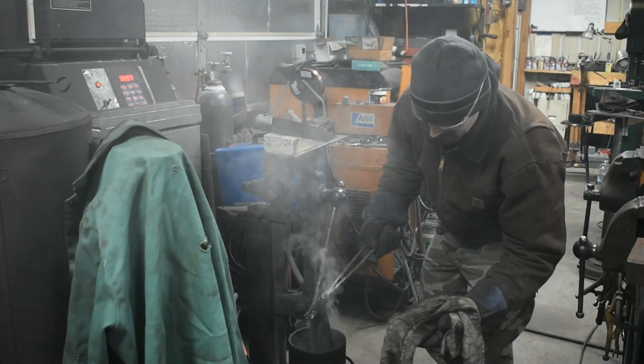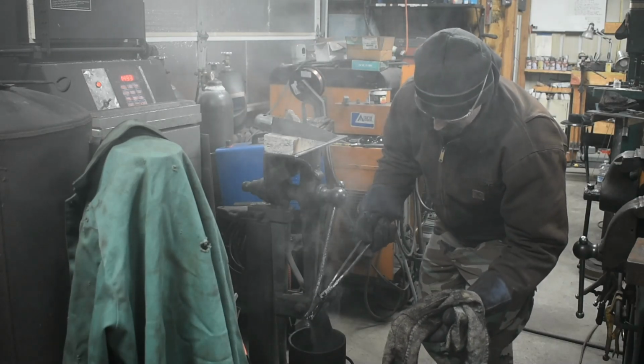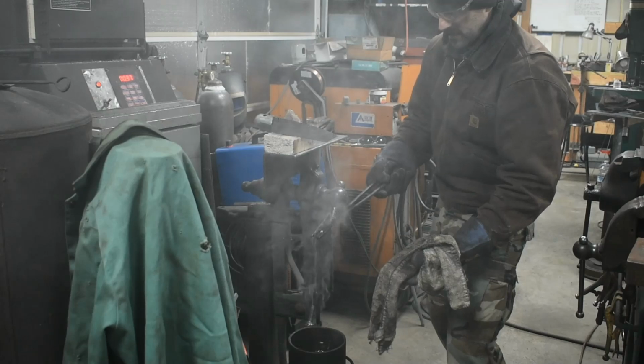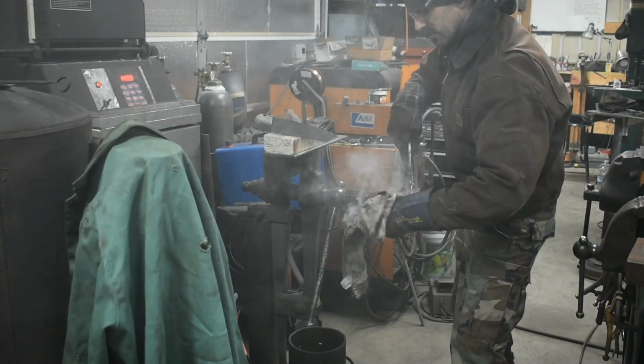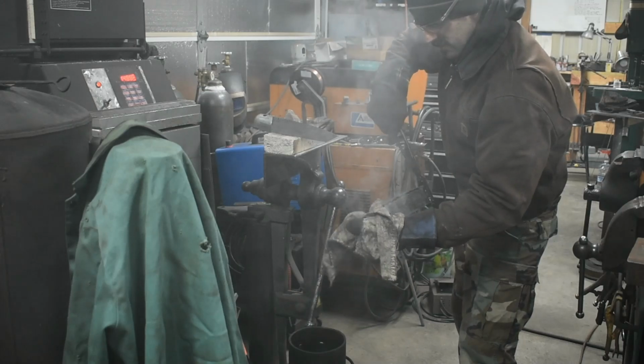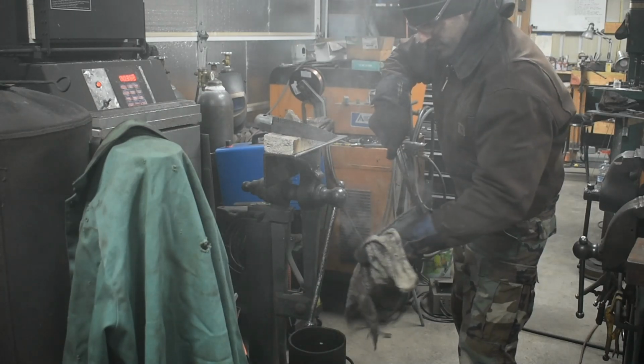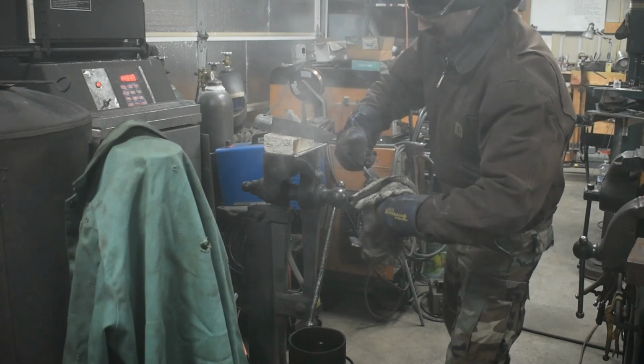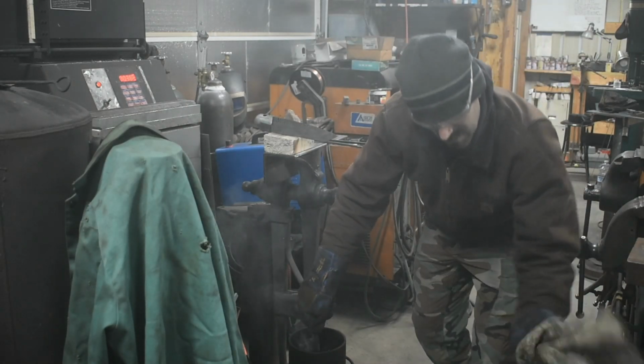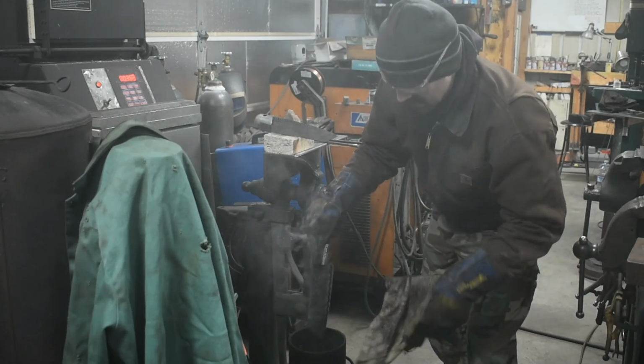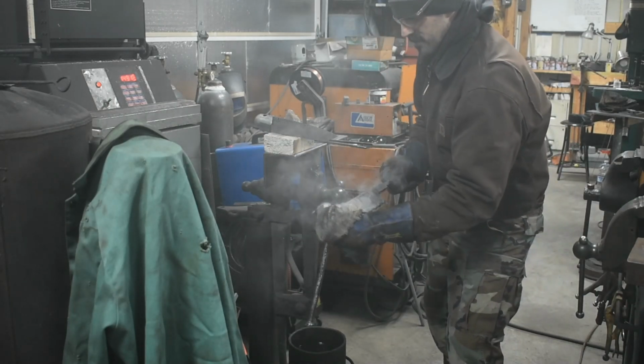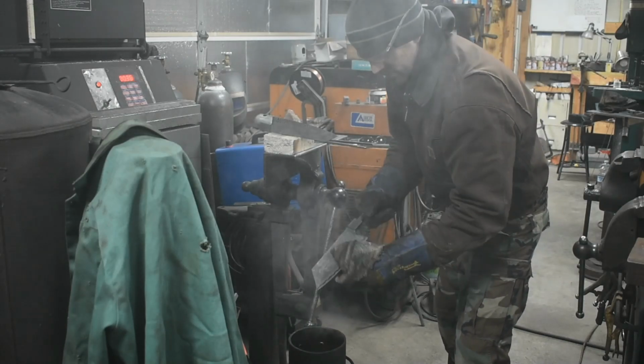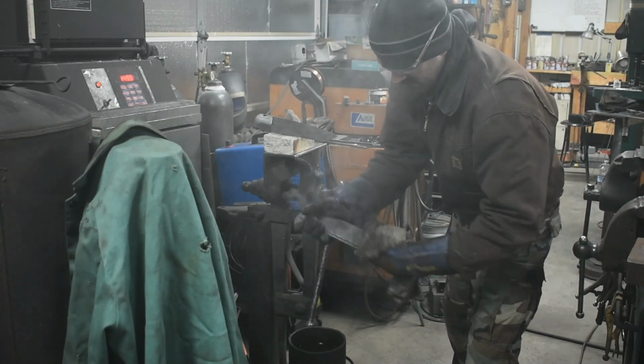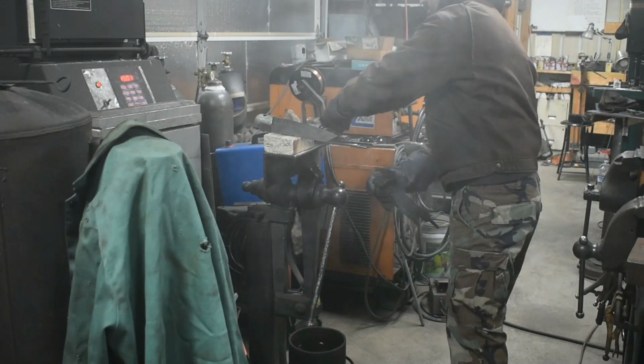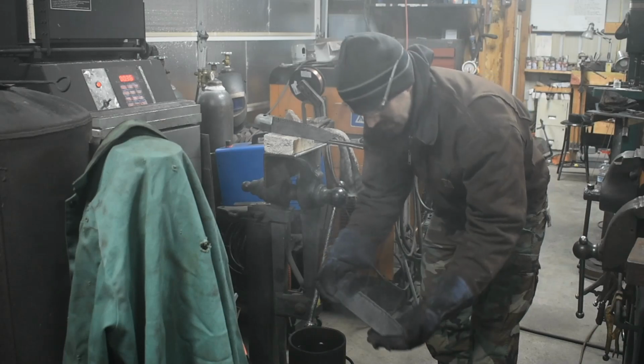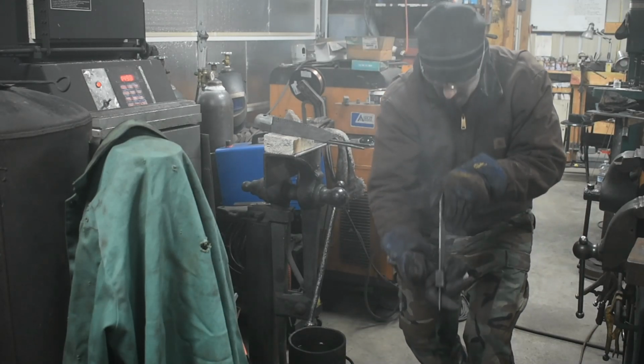Now, with me pulling them out of the oil before they get down to martensite finish, or even martensite start, they will inevitably auto-temper a little bit. So as quenched, you don't get as high of Rockwell readings, but after temper, it evens out. I temper them at a little bit lower of a temperature, and it evens out. I can still get nice hard blades, but I get much less warping this way and much more fixable warping if it does happen. This is particularly useful with sanmai blades that might want to rip down the center of the core. I'll do an episode on that sometime too.